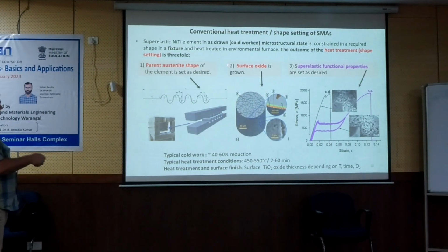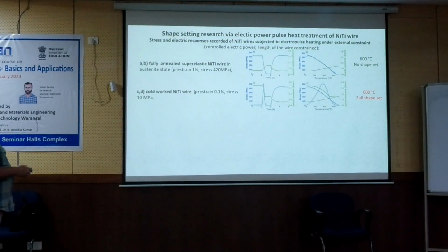But at the same time, you have this surface oxide which grows on the surface, and at the same time, you change it from the cold work state to the functional state. So you imagine now, if you do the shape setting of nitinol, you have to bear all this in mind. So the temperature and time must be set up in such a way that you obtain the shape, you obtain the properties, and you have a good surface.